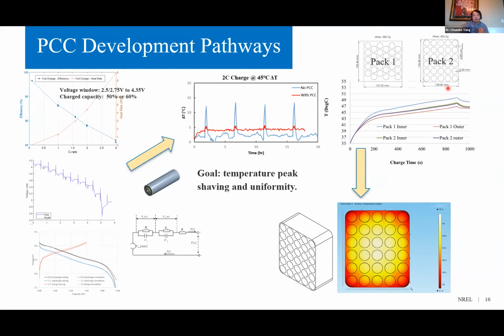Quickly comparing Pack 1 and Pack 2, as you can see, in Pack 2 the cell is relocated. The weight of the phase change composite housing case of Pack 2 is reduced by about 10%. Simulation results show the temperature difference of Pack 2, and it can maintain the minimum temperature difference among the cells.